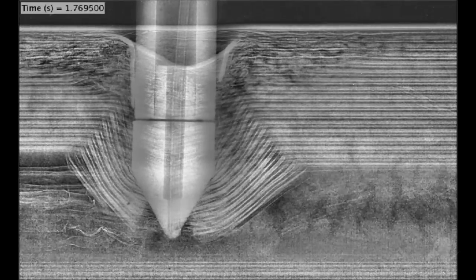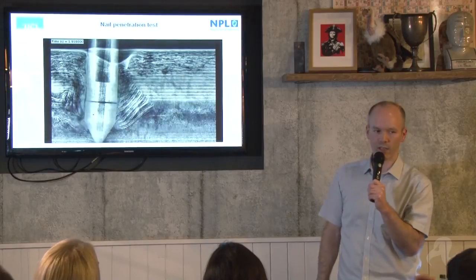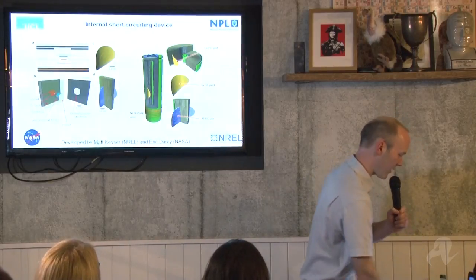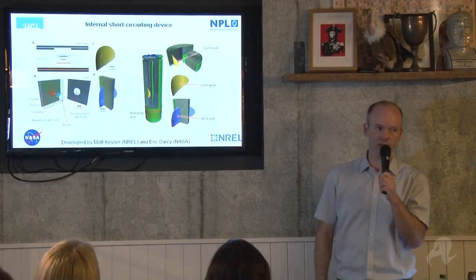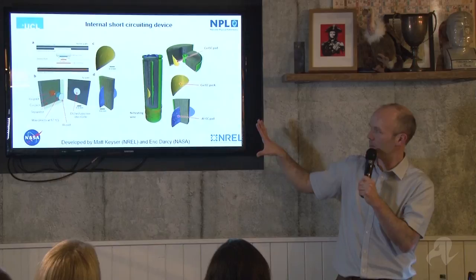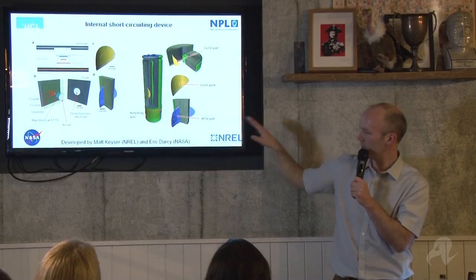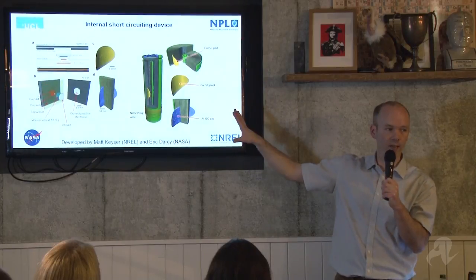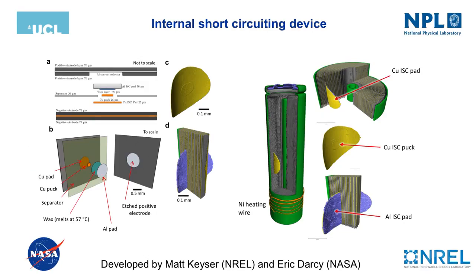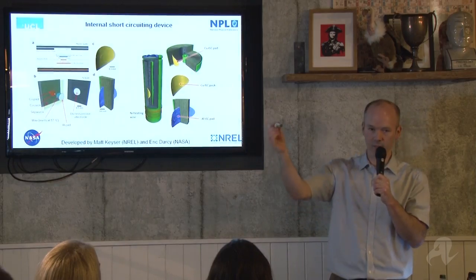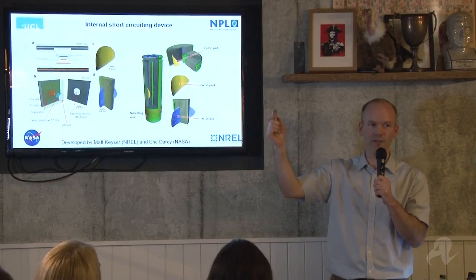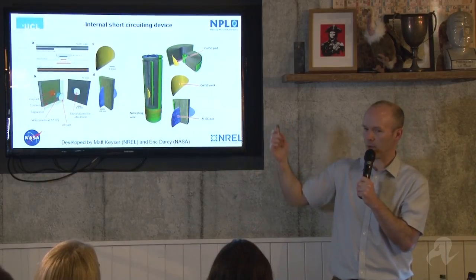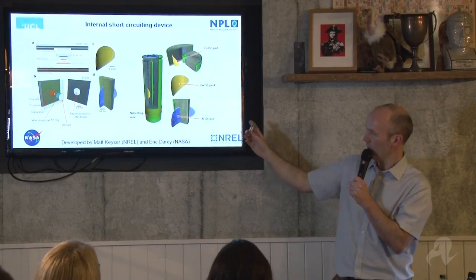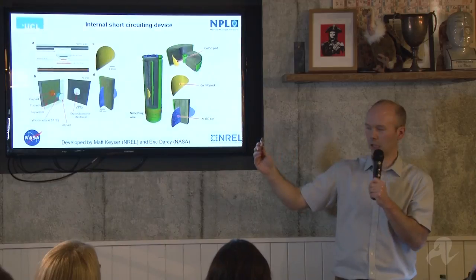At this point, we decided to team up with NASA and the National Renewable Energy Laboratory in the USA, because they had just invented a very clever device called an internal short-circuiting device. So now our collaborative group has got a little bit bigger. There's us, there's UCL, there's NASA, there's NREL, and we did this work again at the European Synchrotron in Grenoble. What's clever about this device is it's trying to replicate a local short circuit in one of these 18650 cells. Hammering a nail through one is literally a blunt instrument. It doesn't really replicate the type of failure that you get in real life. This doesn't exactly replicate it either, but it's a heck of a lot closer.